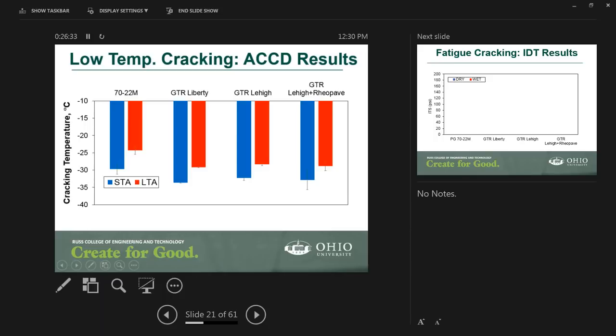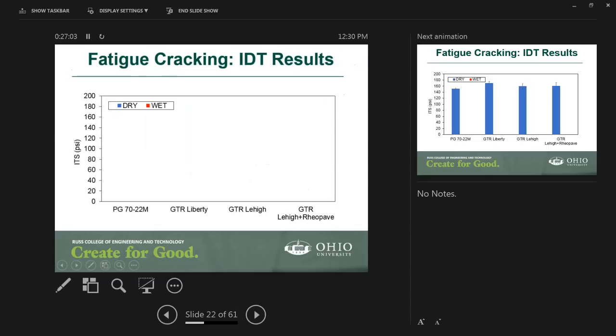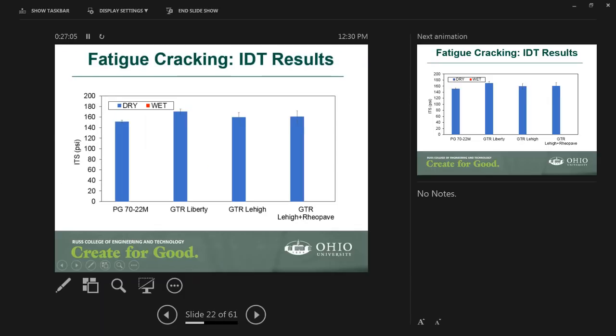One of the things is that in all cases, the cracking temperature, which is the temperature that we expect the asphalt mixture to crack in the field, or the lowest temperature that an asphalt mixture will crack in the field, was basically colder, so it was better. So this means it is an indicator that it had a slightly better low temperature cracking resistance as compared to the 70-22 polymer modified.